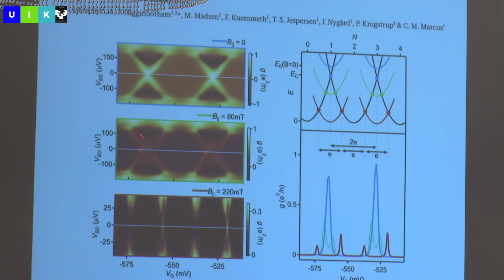If it's an Andreev state and it's away from 0, you get little step, big step. And if the Andreev state is all the way up at the gap, you get 2e. So here's this level moving down from bigger than the charging energy to smaller to all the way down to 0. And yet you can see the structure that shows that there's a subgap discrete spectrum.